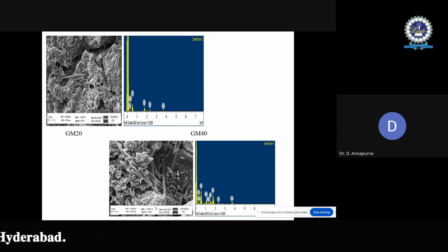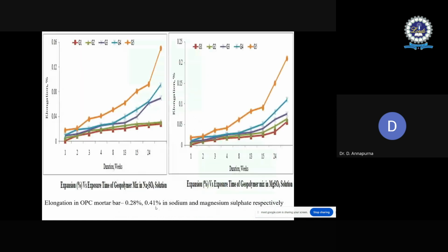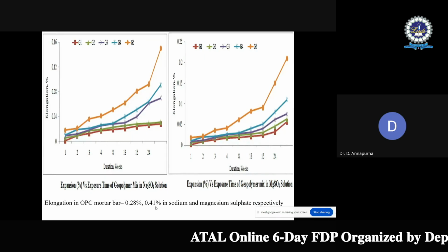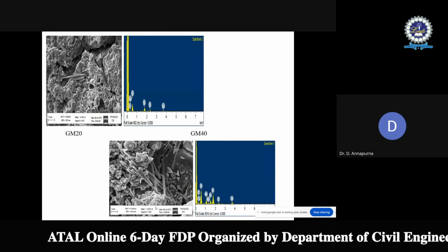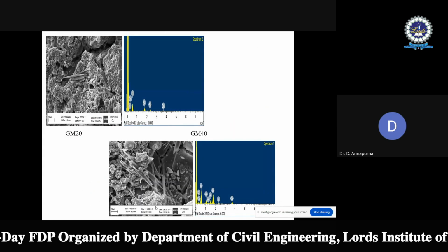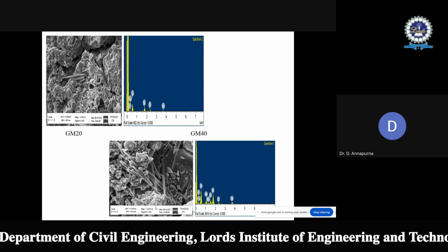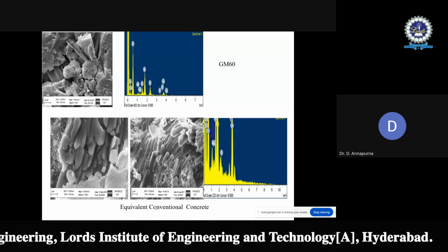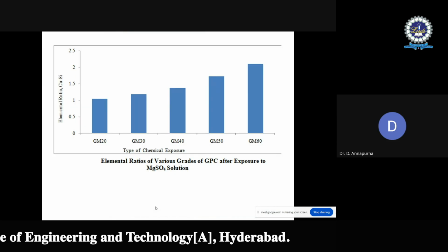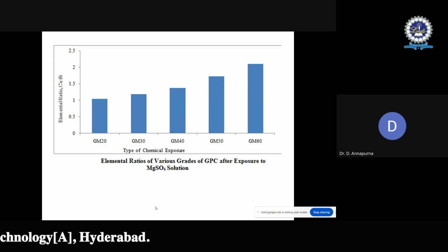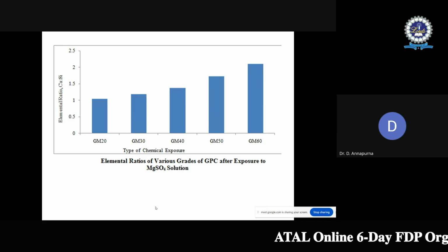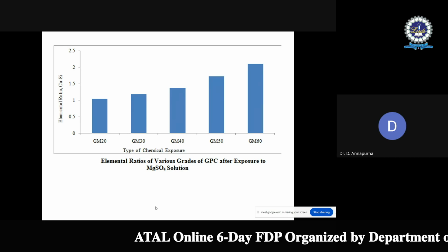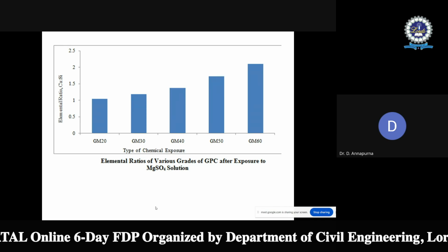SEM pics are also taken of the same geopolymer concrete specimens, again immersed in sulfate solution. The SEM pics are also confirming the presence of aggregate formations, as seen in these pics. Okay. Next, the elemental ratios. Elemental ratios confirm how the magnesium sulfate is influencing the properties of the proposed geopolymer concrete.